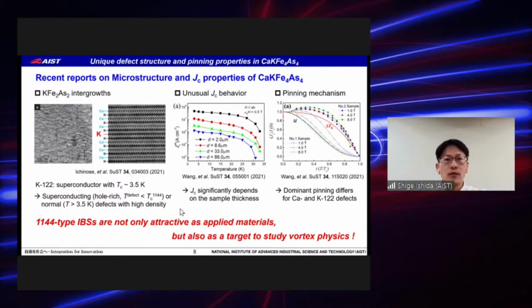Actually, I have no clear idea about the coexistence of calcium 122 and potassium 122, because to my experience, maybe these intergrowths appear because of some imbalance of chemical composition during the crystal growth. If locally potassium becomes rich, we observe calcium 122 or potassium 122 intergrowth. So if we obtain a very, very large crystal and separate it into several pieces and check carefully, we may observe some coexistence of these two kinds of intergrowths. But if we observe locally, maybe it's dominated by either calcium 122 or potassium 122.